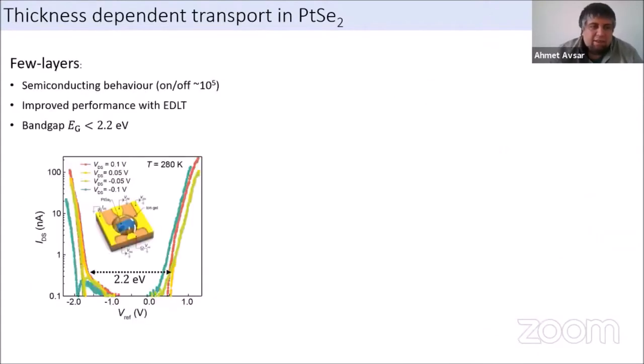We have also used a technique called ionic liquid gating to measure the band gap of this material. Basically, it allows you to apply more capacitance, like more effective electric fields. Therefore, you can really go from the conduction band all the way to the valence band. And then, also using some references, at the end of the day you can extract the band gap through the transport. So we got the band gap experimentally in the order of 2.2 eV.